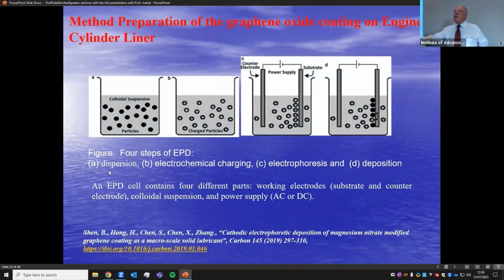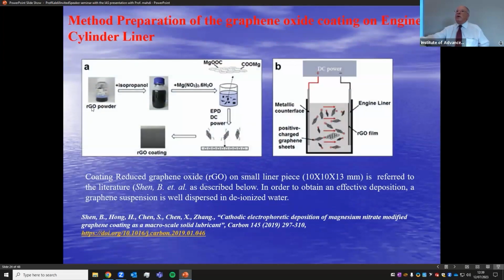And for the process, we have 4 steps: dispersion, electrochemical charging, as you know, electrophoresis, and deposition. So we use this recipe from the literature, from this paper. We have RGO powder, and we have isopropanol. We mix isopropanol with RGO powder. Then we add the magnesium nitrate, and we have the EPD process. Then we coat the engine cylinder liner here. I will show you later.